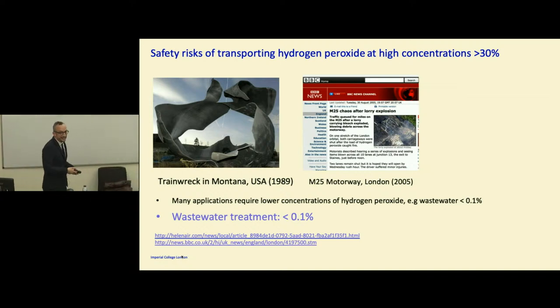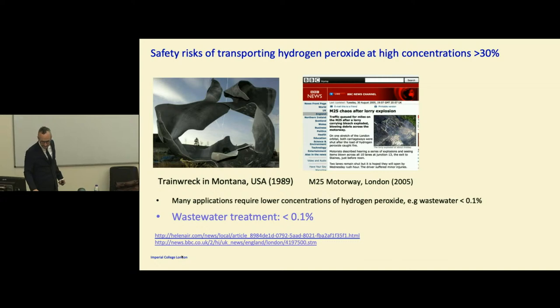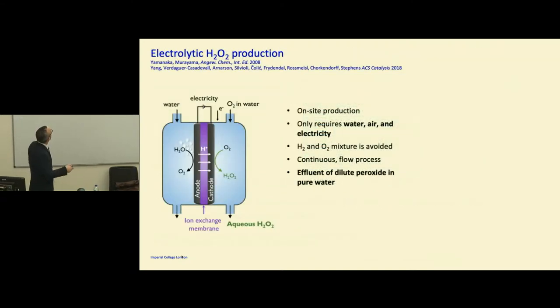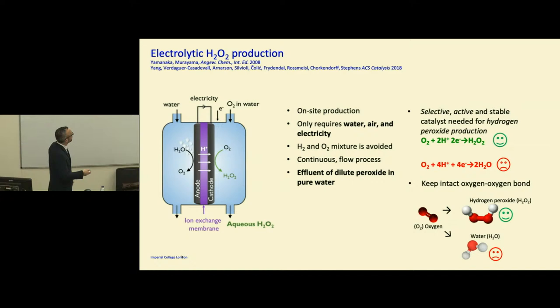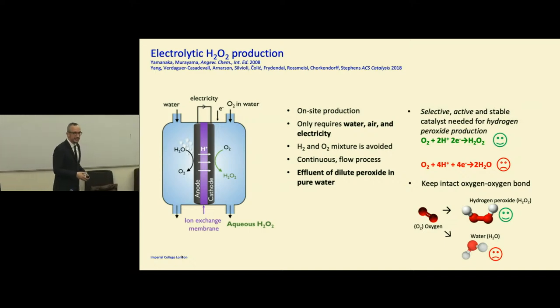We said, well, actually, you can. We didn't really understand why people were not trying to do it. So essentially, all you need is water and oxygen and electricity, and then you can get dilute peroxide in pure water. What's really important is that you keep intact this oxygen-oxygen bond and don't make the more thermodynamically stable product, which is water. So we started looking at the literature, and people had been able to do it, but they were not doing it particularly efficiently.